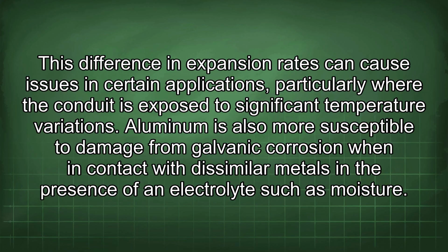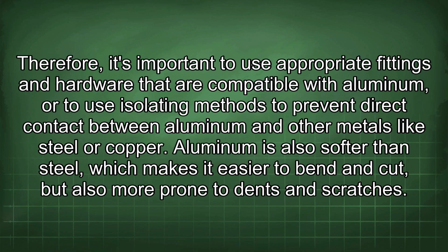variations. Aluminum is also more susceptible to damage from galvanic corrosion when in contact with dissimilar metals in the presence of an electrolyte such as moisture. Therefore, it's important to use appropriate fittings and hardware that are compatible with aluminum, or to use isolating methods to prevent direct contact between aluminum and other metals like steel or copper.